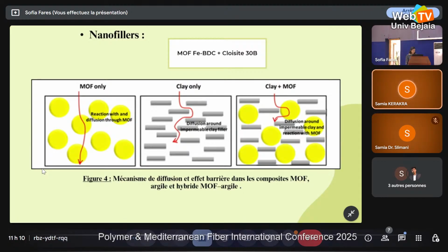Now, in the case of the MOF-only system, molecules can diffuse through the porous MOF particles. If you take the clay as the only system, diffusion is forced to go around the impermeable clay layers, increasing the path length slightly. But if you take the combination of both, both effects occur. So diffusion must travel around the clay layers and interact with the MOF structure, creating a tortuous and complex pathway that strongly reduces permeability and migration. This synergistic mechanism explains the enhanced barrier properties observed in our system, as we will see in our results.